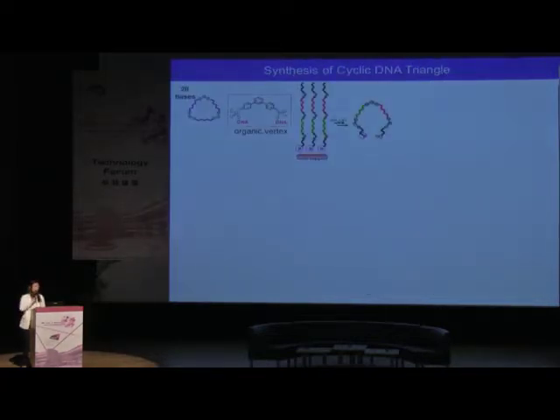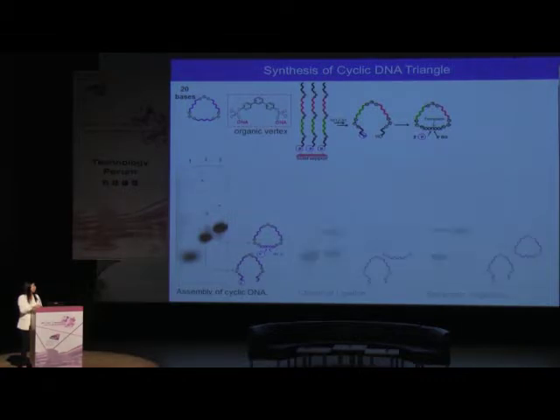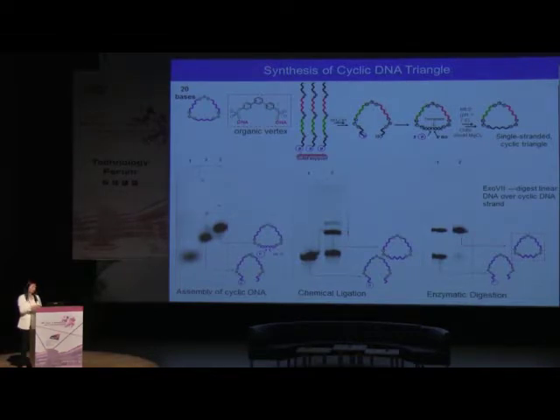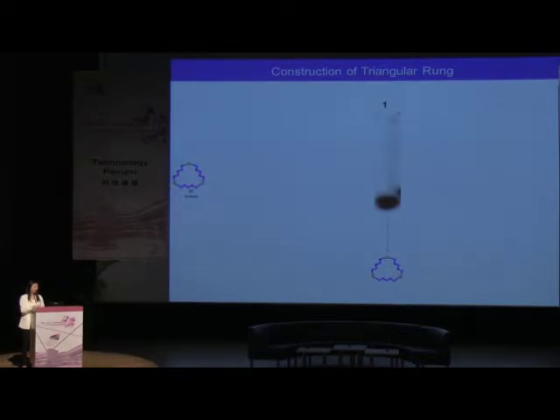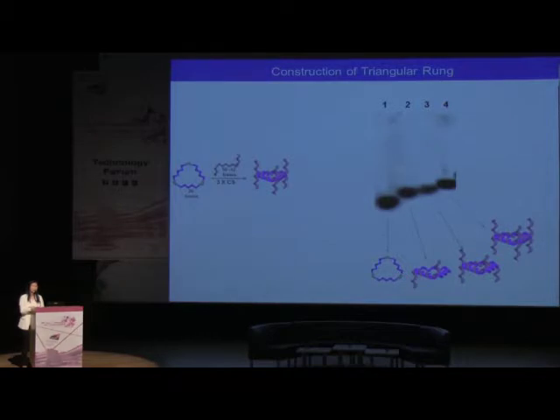So to do this, first of all, we have to grow or synthesize the DNA strand on a solid support using the DNA synthesizer. And here we would like to incorporate this organic molecule between the DNA strands. And after that, we cleave them from the solid support, and we close both open ends using a template to carry out the chemical ligations. So once we have this DNA single-stranded cyclic triangle, what we have to do is add and design 3 complementary DNA strands here, one by one, to form this rung. And finally, we rigidify this using a short DNA strand here. So at the end, you can see this triangular rung with 3 arms pointing up, and the other 3 arms pointing down.